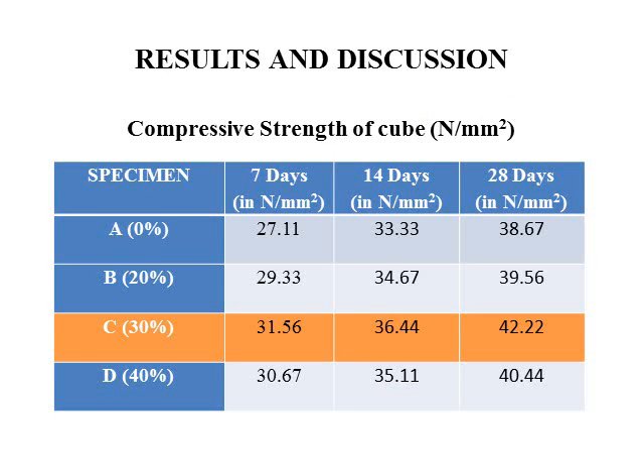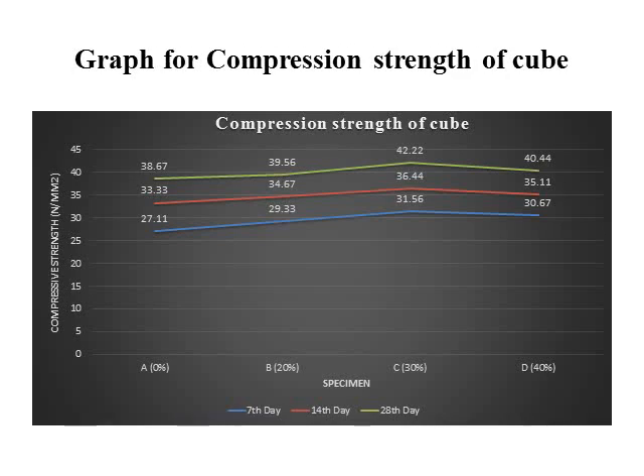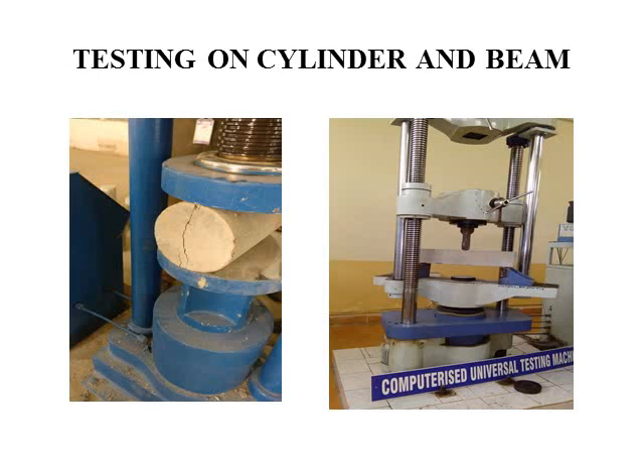Results and discussion. The compression strength of cube was found to be increased at 30% replacement of marble powder with fine aggregate. For 7 days it was increased to 31.56, and for 28 days we have got the strength as 42.22. It is the peak strength. This is a graph showing the compression strength of cube, and the maximum peak was found at 30%.